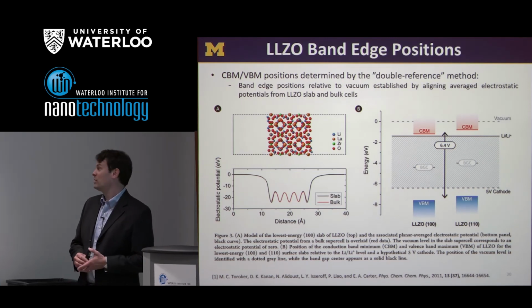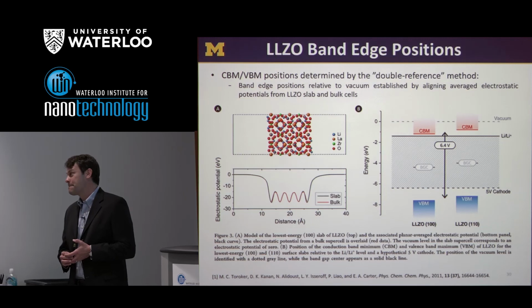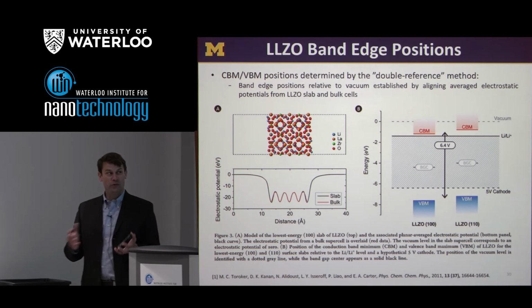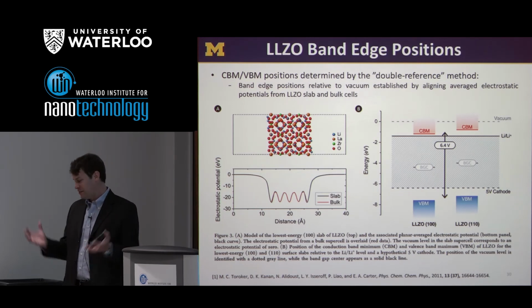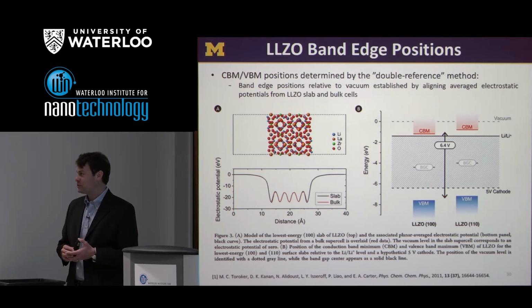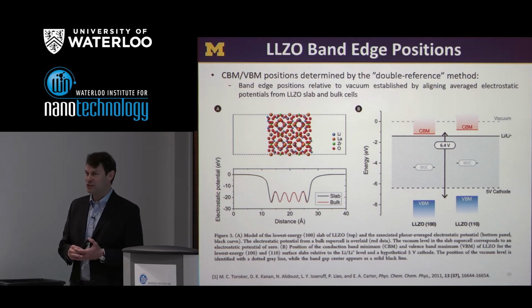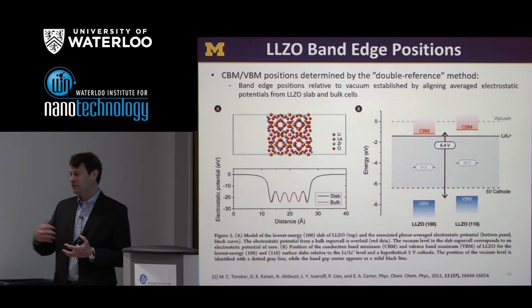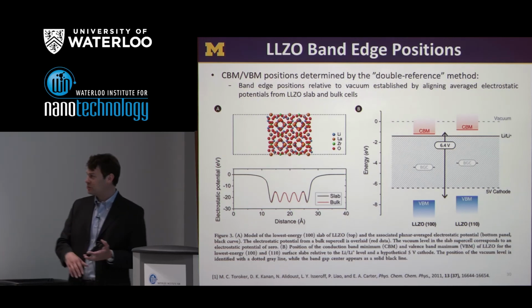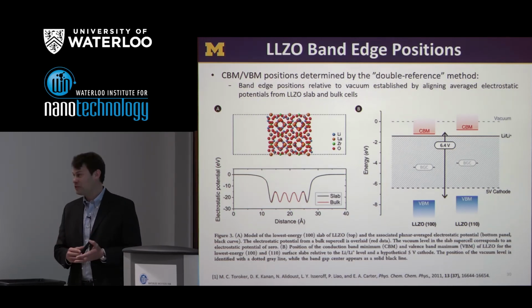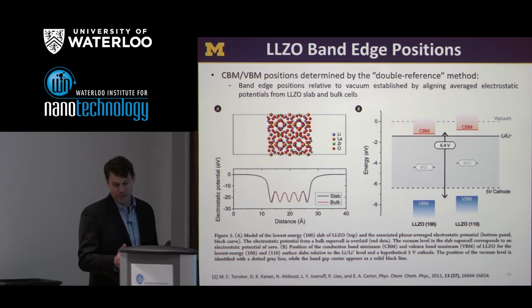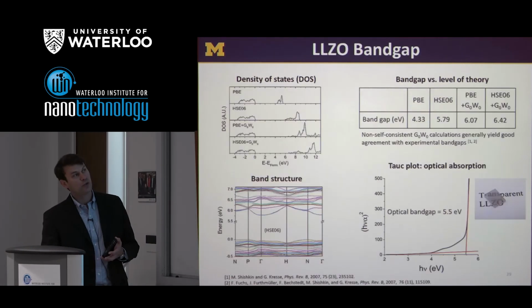So for the grain boundaries, you're assuming no change in concentration, stoichiometry? We're assuming that the whole cell remains at the stoichiometric LLZO composition. We haven't done an open system calculation where, for example, we could make the system oxygen rich or oxygen poor. That could be something which is done, but is not something we've done at this stage. I'm also thinking you might get rearrangement. Well, the calculations here do allow for atomic relaxation.